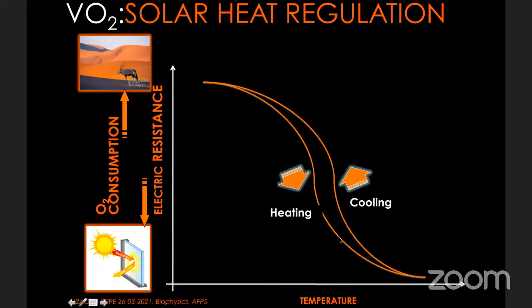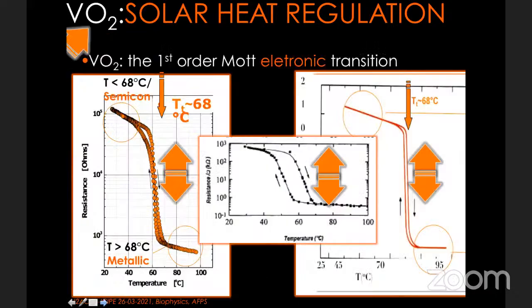And it does it in a reversible way. So we are looking for a material which would behave like this, like in this hysteresis. At a high temperature, it has to have low resistance, instead of oxygen consumption. So the equivalent of the oxygen consumption should be the electric resistance. So the material that we are looking for should have low resistance at high temperature and high resistance at low temperature. And such a material is an old one, which is called vanadium dioxide.